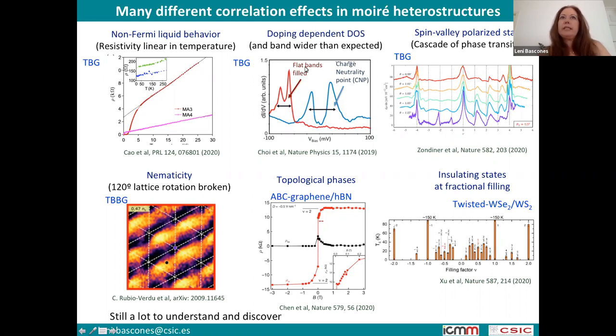As you can see here, this is clearly a non-rigid band shift, and here, when it's away from the insulators, there is what has been called the cascade of phase transitions, which has been interpreted in terms of spin and valley polarized states. There are nematic states in which the rotational symmetry of the lattice has been broken. There are topological phases. There are also insulating states at fractional fillings.